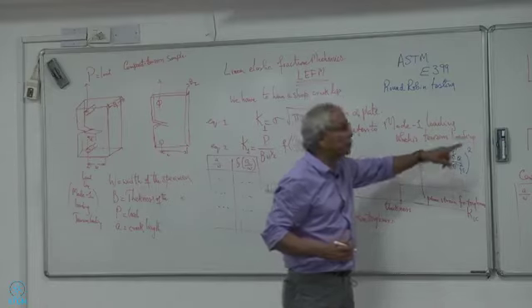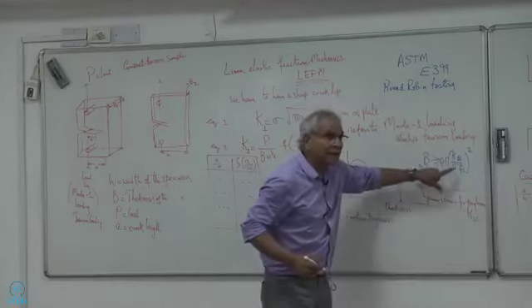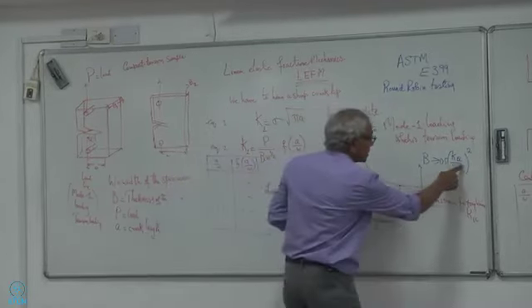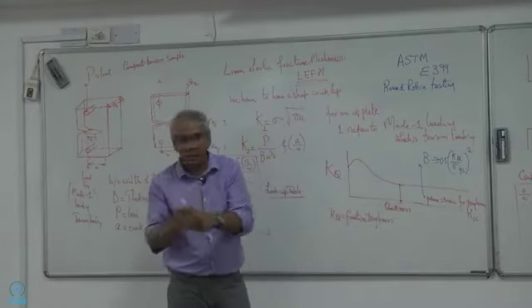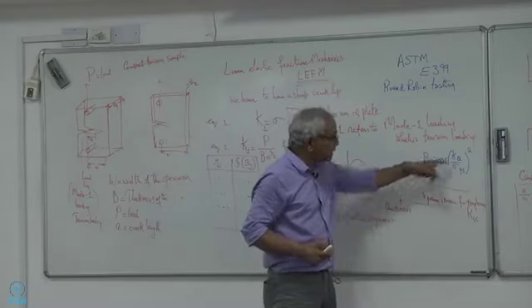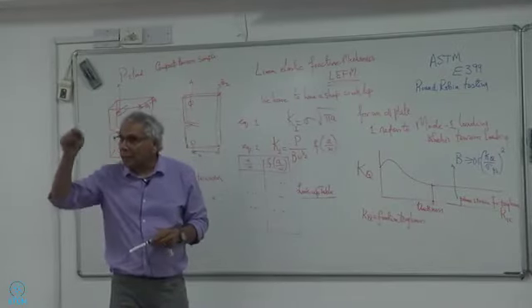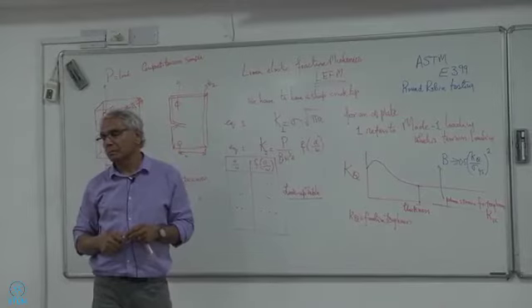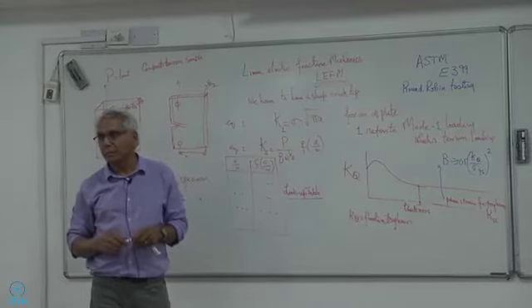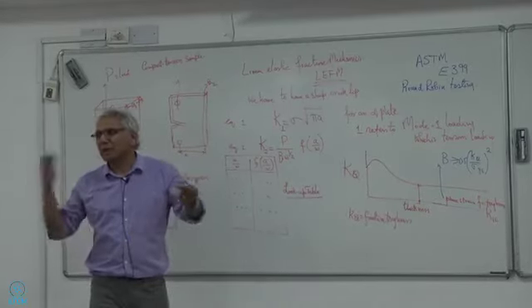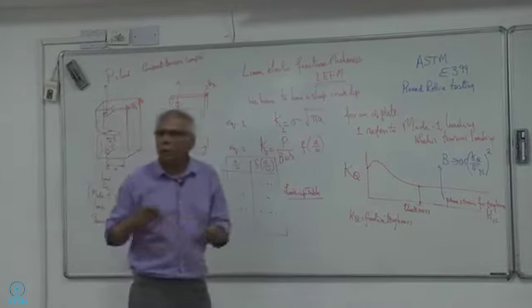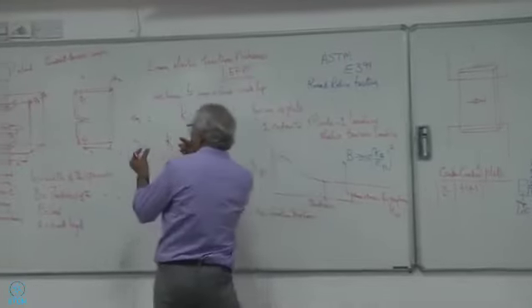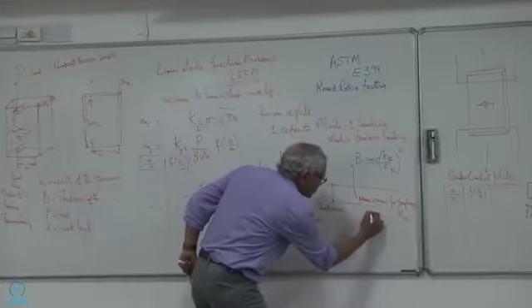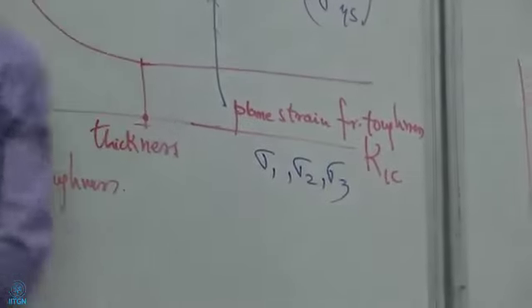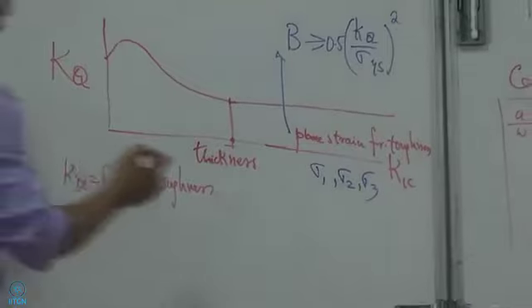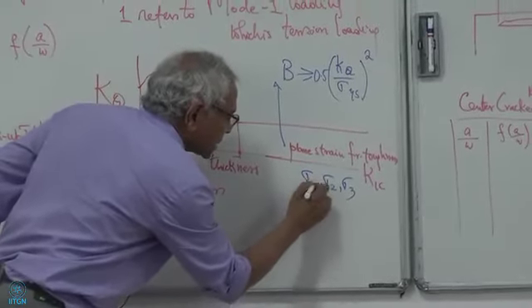So when I get this K sub Q number from here, I divide that by the yield stress of that material, I square it and I multiply that by two point five. The thickness has to be greater than that. If it is, then I have met the plane strain conditions. And why did I say it's a poor man's definition? Because I'm not talking in terms of stresses and strains. In terms of stresses and strains, what plane strain conditions really mean is that because it's a thick specimen, I have sigma 1, sigma 2, sigma 3, and I have U displacement. Let me put this as X. It may be easier.